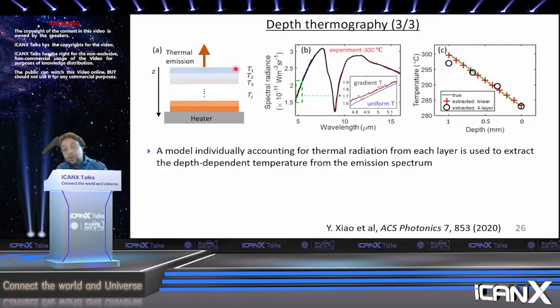And so what we do is we essentially have a forward simulation that we perform based on the fluctuation dissipation theorem that can take in any set of these discrete temperatures and figure out what the resulting spectrum is going to be. And then we fit that model. So we are essentially fitting all of these individual temperatures to try to match the experimental spectrum as well as possible. And then ultimately we're able to get a measurement of the temperature as a function of depth. So this is exactly depth thermography.